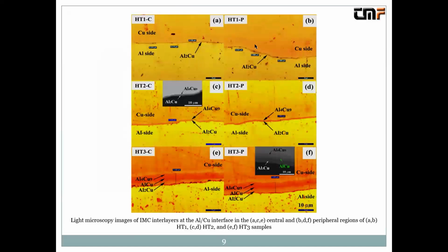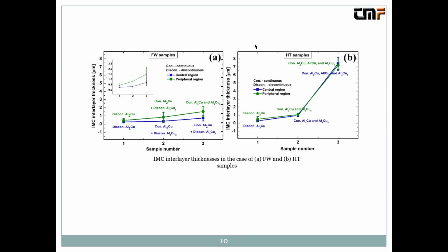And when we are talking about the samples which were heat treated, all the samples show continuous intermetallic layers all over the surface. So what's the difference? The first one contains only an Al2Cu intermetallic layer. Then the second one contains also Al4Cu9, and the last one, as you can see, contains AlxCuy intermetallic layers, which are formed between those two intermetallic layers. And as I said, they improve a lot the mechanical properties of the joint.